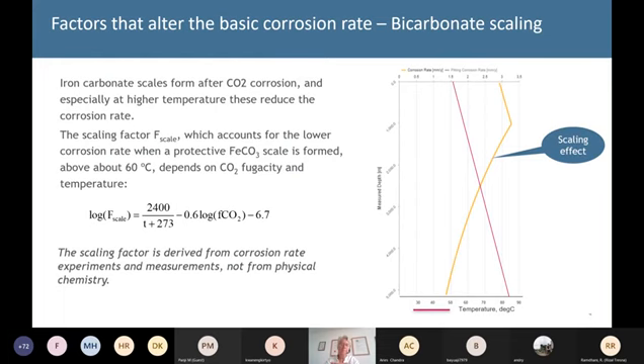And we have therefore to consider that the corrosion rate, whilst it normally increases with increasing temperature, reaches a point at which the protectiveness of the scale starts to counteract that, and we get a drop-off of corrosion rate. And so we have this scaling effect, which is derived both from laboratory experiments and also from observations in the field. And the actual scaling temperature is not always the same, but typically between about 55 and 75 degrees C, we start to see this drop off.